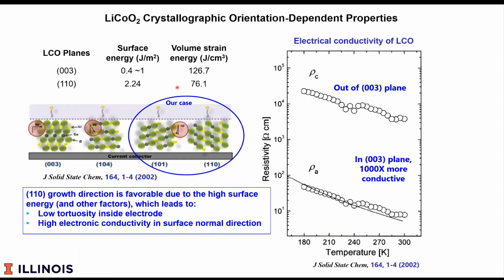So a little bit about the properties. The electrical conductivity, this is why this is so important. The electrical conductivity in and out of the (003) plane varies by 3 orders of magnitude. So if the (003) planes are oriented like this and you're trying to drive electrons this way, the transport is very limited. Of course, when the planes stand up like this, you're going down the fast transport direction.